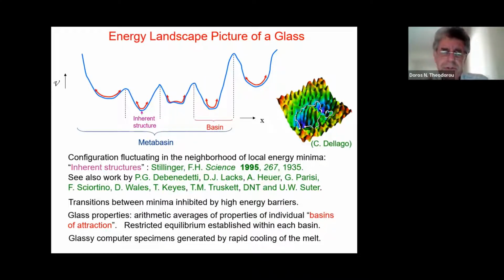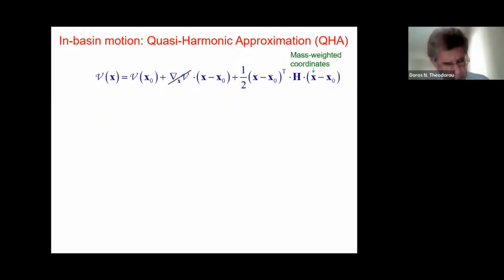So our first concern in simulating a glass is to form specimens of this polymer from an equilibrium melt by rapid cooling from the melt, and we do so with molecular dynamics. So we cool a melt, we quench it, and we trap it within local minima of the potential energy with respect to configuration, to configurational degrees of freedom. As long as this glass is trapped in the vicinity of a minimum, we expand its potential energy with respect to its microscopic degrees of freedom out to second order. It sits at a minimum, so the gradient of the potential energy is 0.